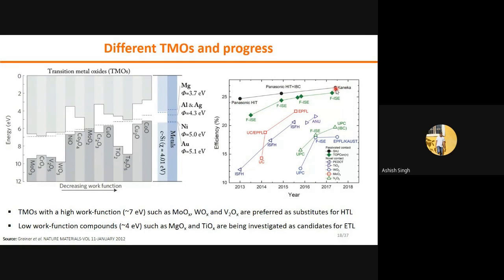So this is a transition metal oxide, and with the help of passivated contact solar cells, people started working, and the highest efficiency reported by EPFL was 23% from moly oxide, a transition metal oxide hole transport layer. So this can show us the hope to reach from here to here.